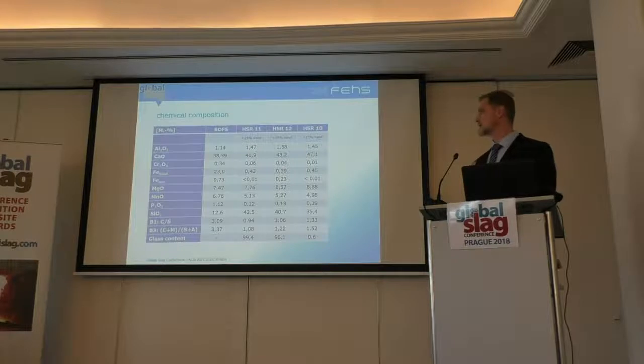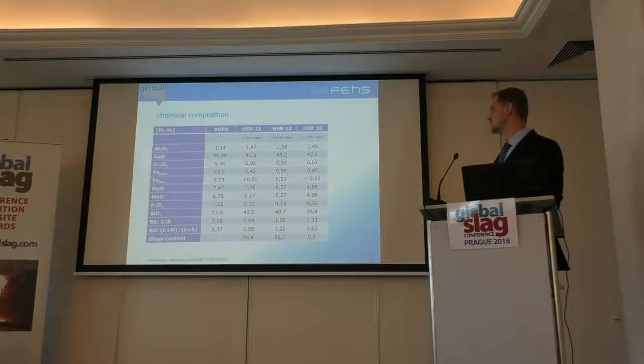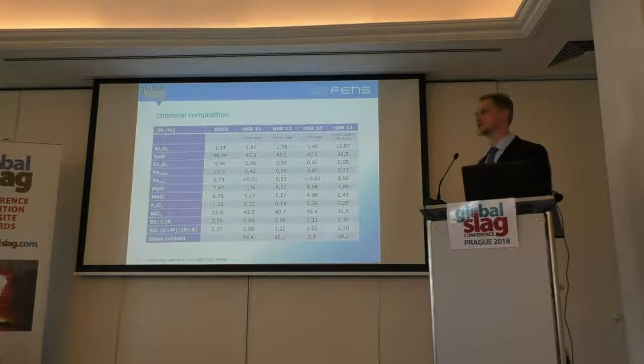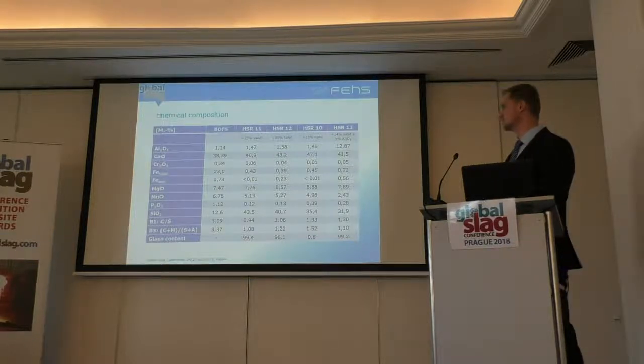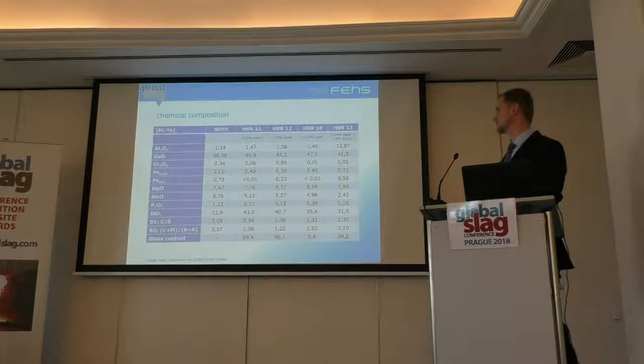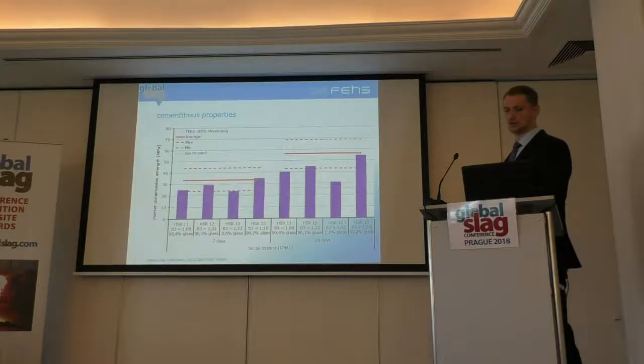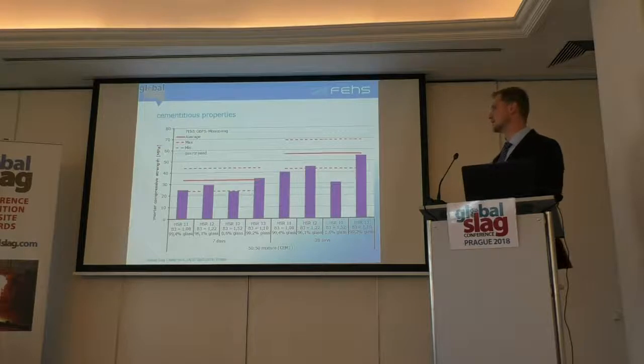So we look not just to the simple basicity, we look to the B3, the one especially with alumina. And here you can see we are at 1.5, that is very, very high. And we try to keep this CaO/SiO2 basicity at 1.3, but to increase also the alumina content. That was also just one trial to get a glassy material and to look, okay, how it looks like from the cementitious properties. We got 99% glass, a high CaO/SiO2 basicity, and with this we go to the cement laboratory.